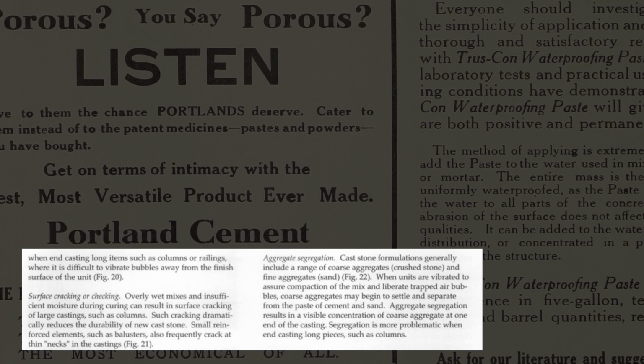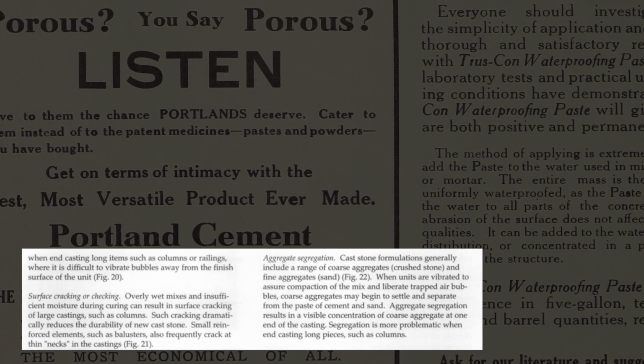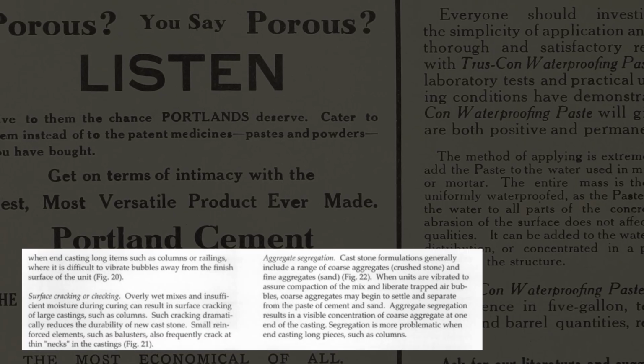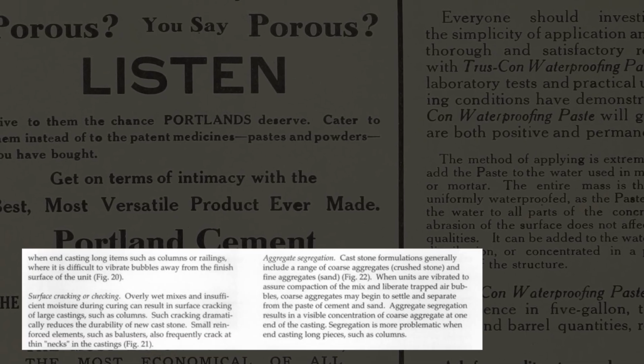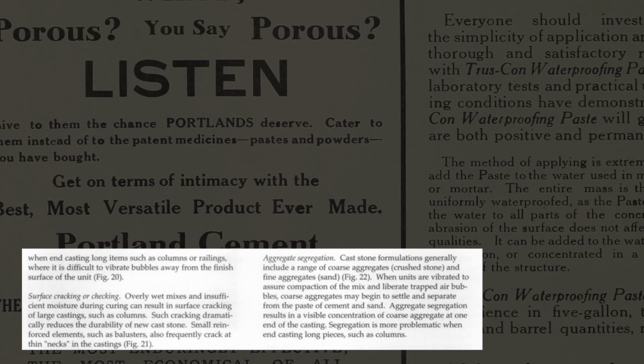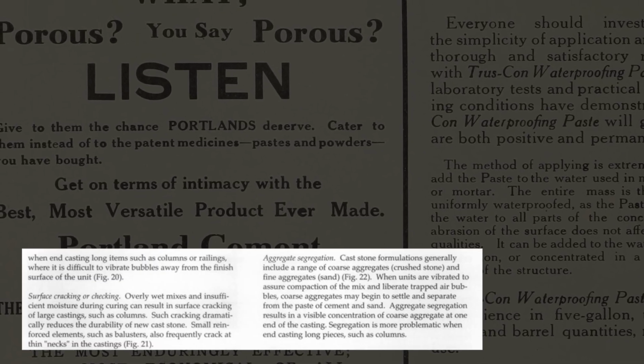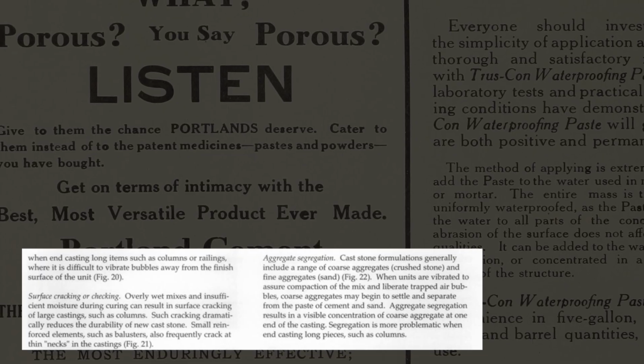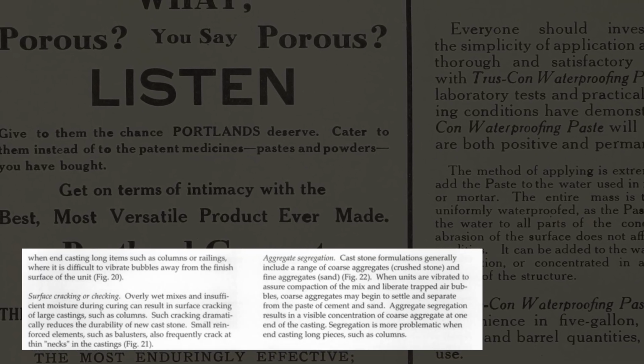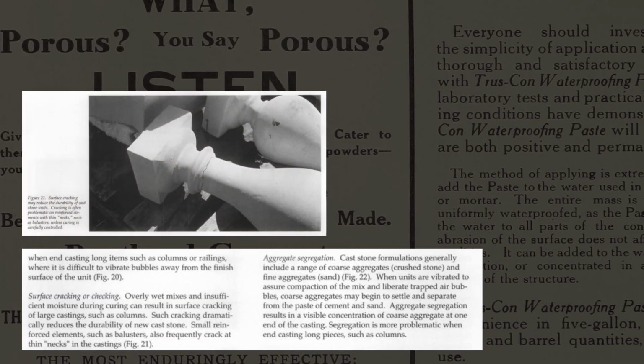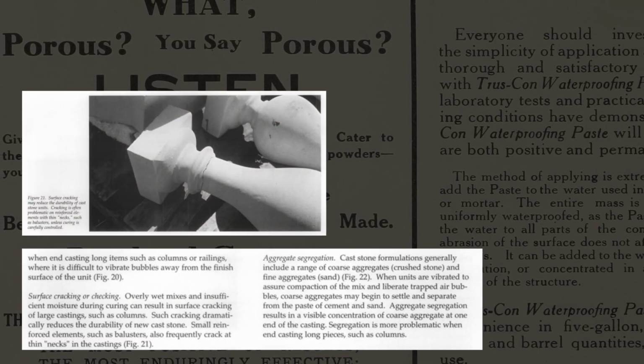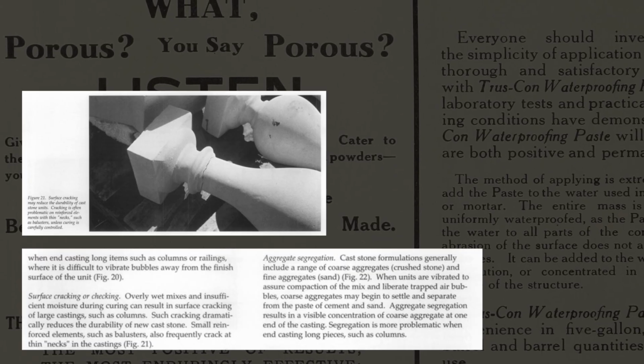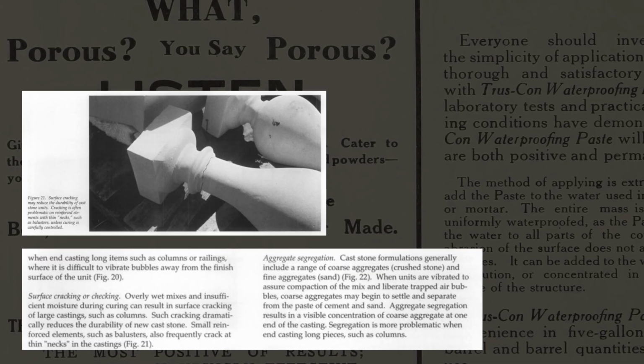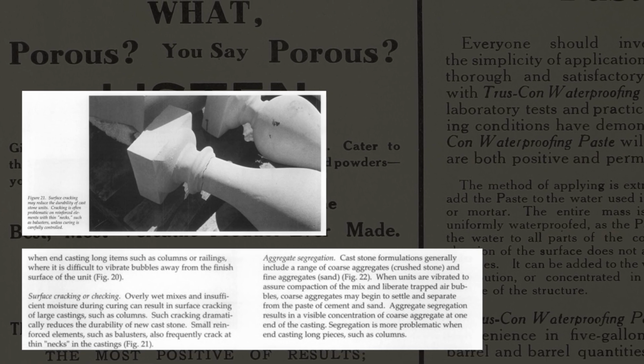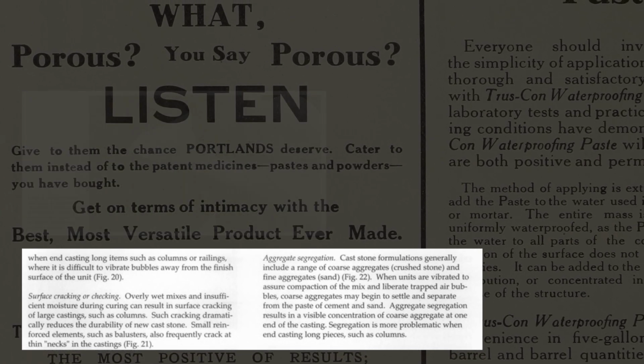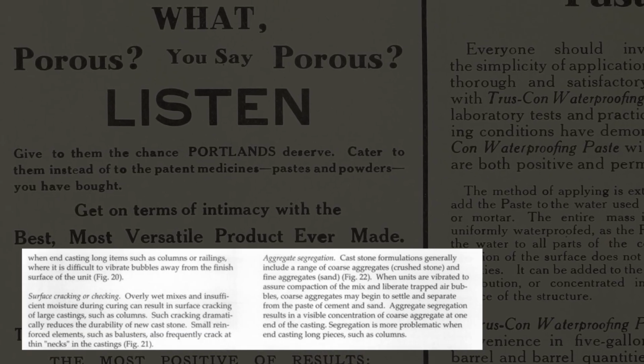Surface cracking or checking. Overly wet mixes and insufficient moisture during curing can result in surface cracking of large castings, such as columns. Such cracking dramatically reduces the durability of new cast stone. Small reinforced elements, such as balusters, also frequently crack at thin necks in the castings. And here we have an example of that with figure 21, reading as follows. Surface cracking may reduce the durability of cast stone units. Cracking is often problematic on reinforced elements within thin necks, such as balusters, unless curing is carefully controlled.